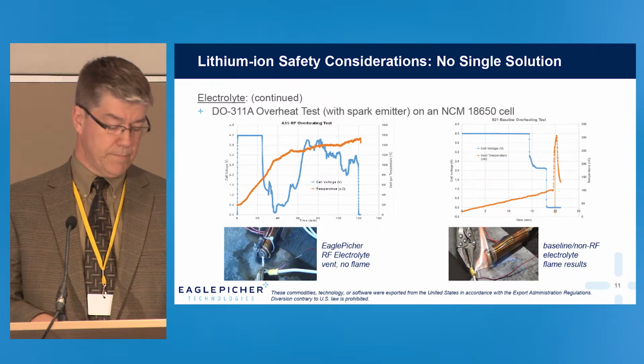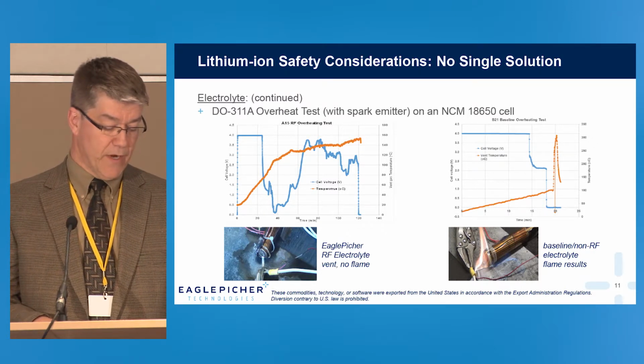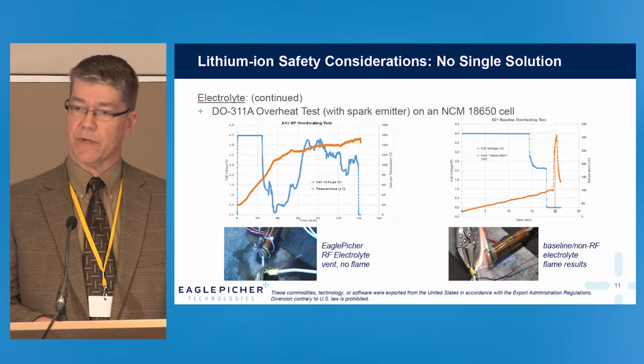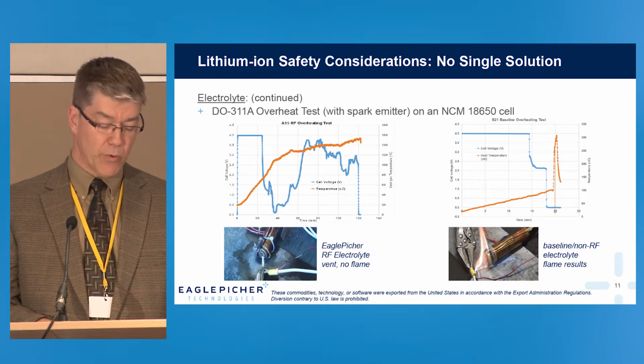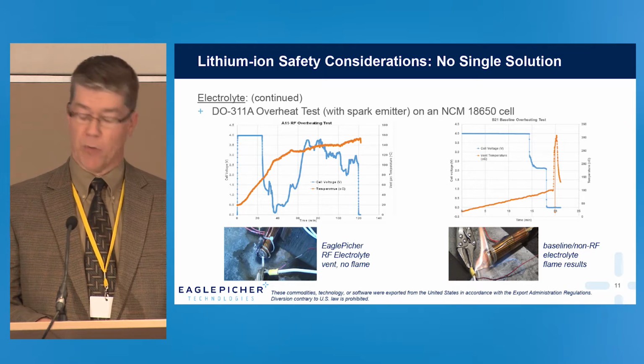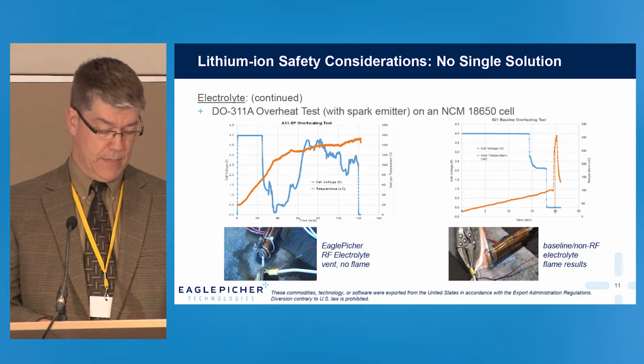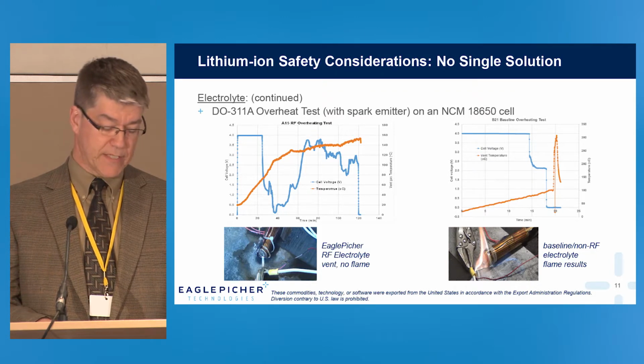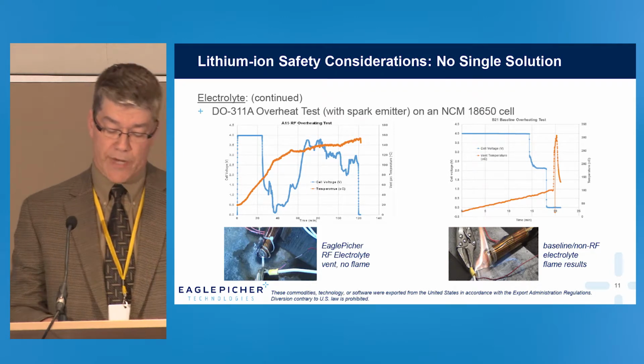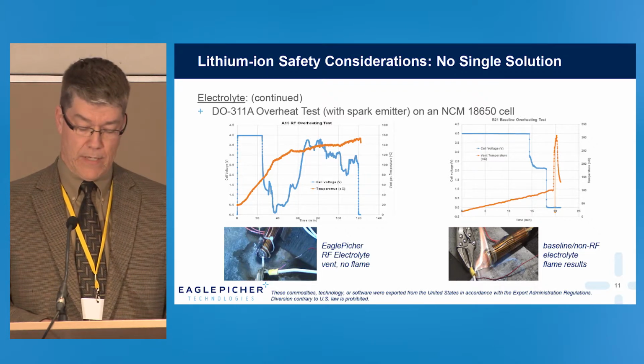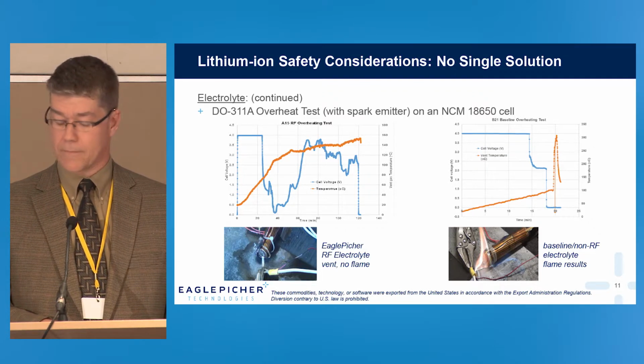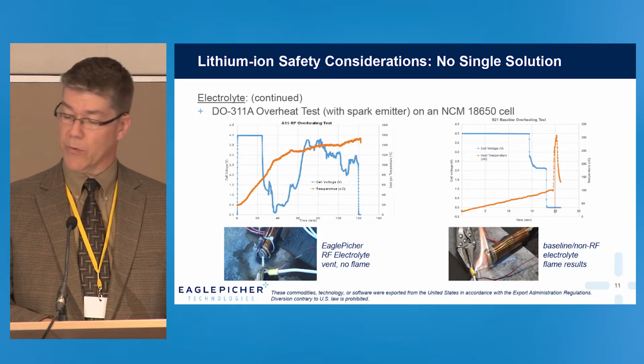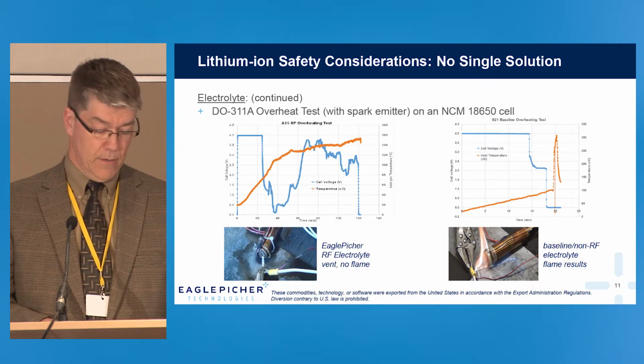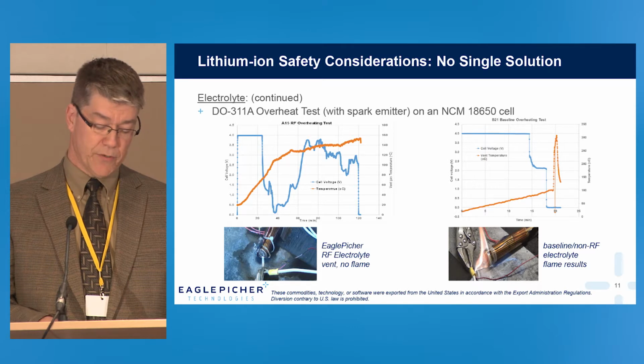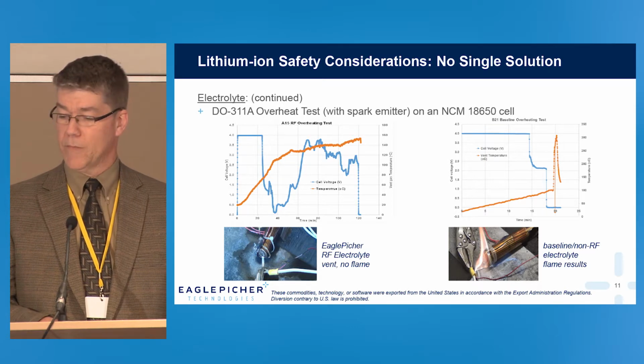Continuing to look at the electrolyte, we modified a DO311A overheat test that we mentioned earlier to now include a spark emitter. And we compared the baseline response to that of EaglePicher's reduced flammability electrolyte. So here on the left, we can see that the RF electrolyte supports a more gradual degradation of the NCM cell with no flame resulting. Whereas when we look to the right, we see that the baseline electrolyte is pushed to a significantly higher vent temperature with a resulting flame.